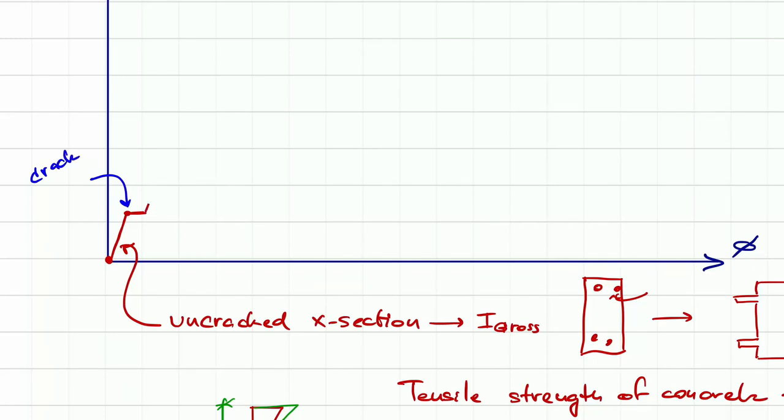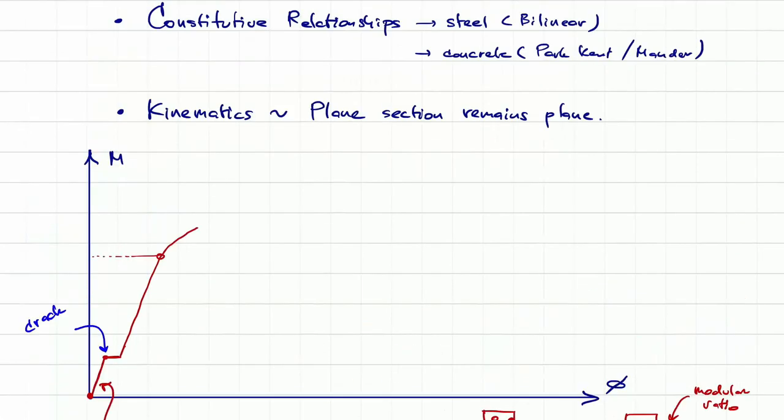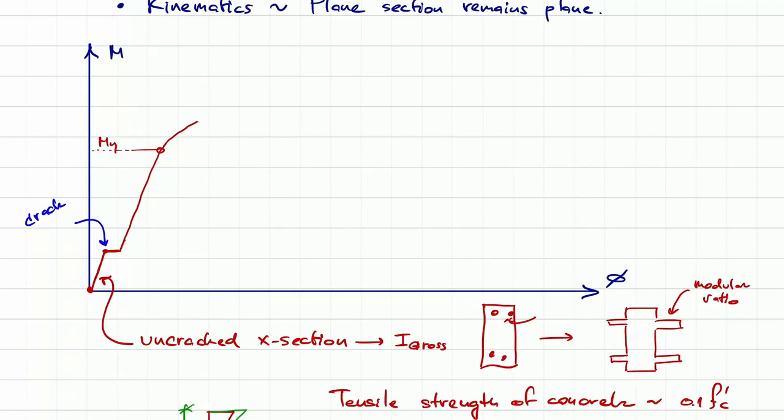After this, it goes up. Okay. So you come to the point where your steel starts yielding. You might end up with the case where the concrete crushes. That's also possible if you put too much steel. Concrete crushes and then it drops. But if your cross section is a good one, you'll be seeing the ductile behavior like that.